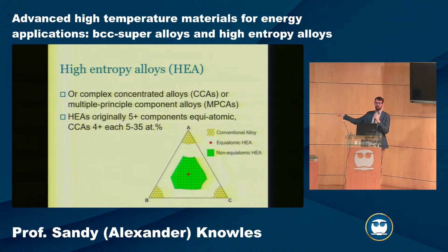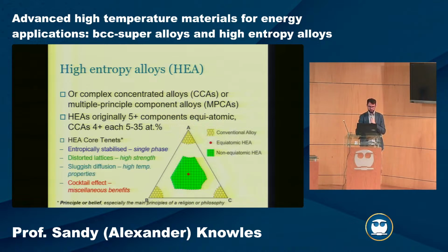The thing which was particularly unusual about high entropy alloys is that when you mix multiple elements together, as we saw in some of the previous work on binaries and ternaries, you often get intermetallics. For example, we added chromium, nickel, and aluminium together, and formed a two-phase equilibrium which contained BCC and nickel aluminium as an intermetallic. What's been quite unusual in a number of the high entropy alloys is that it's possible to form a simple crystal structure, be it BCC, FCC, or HCP, within this complex composition space. And that gives us a new design rule for making new materials.